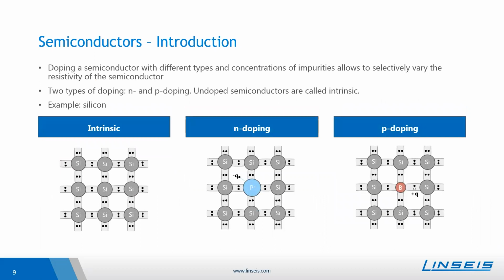An important part of semiconductors is that they can be doped with different types and concentrations of impurities. In this way, it is possible to vary the resistivity of the semiconductor by ionizing these impurities. This ionizing typically happens thermally. One classifies here two types, the so-called N and P doped materials. Semiconductors without any doping, the pure semiconductors, are called intrinsic. To make this a little clearer, we have a look at an example. This here is an example of silicon. Here you have the intrinsic case of silicon, where you see the silicon atoms and how they are bonded.